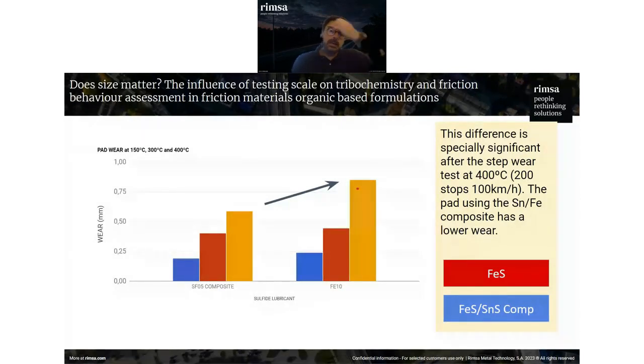Why is the wear higher? That's something probably related to this tribochemistry, and is related probably to the oxidation of the iron sulfide at high temperature. We are getting iron oxide. We don't have anymore the iron sulfide at high temperature. So we are not getting this effect of lubrication or this effect of wear protection of the sulfide at high temperature.